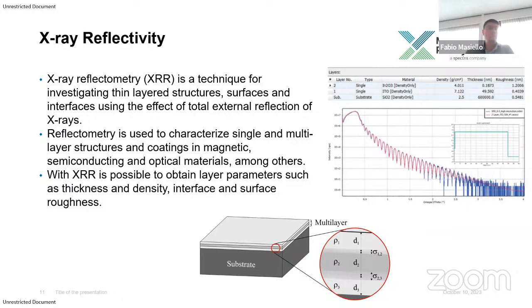Another technique that is very much linked with X-ray scattering is reflectometry. We go again back into thin layer structures, but in this case they don't need to be crystalline. It works with any type of layers, as long as there is a different density between the layers. It is used to characterize single and multi-layer structures, for example in coatings, magnetics, semiconducting and optical materials, among others. The parameters you're looking for by using X-ray reflectivity are the thickness of the layer, the density of the layer, and also the interface and surface roughness.